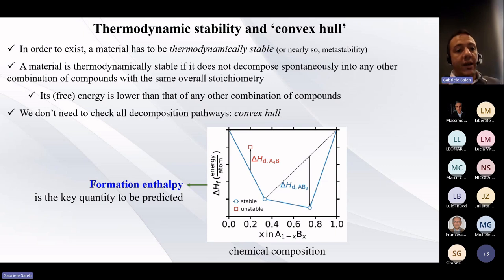Luckily, we don't have to scan all possible decomposition pathways because we use the construct of the convex hull. The convex hull is what you see in this image. In short, it is a plot of the formation energy or formation enthalpy against composition.